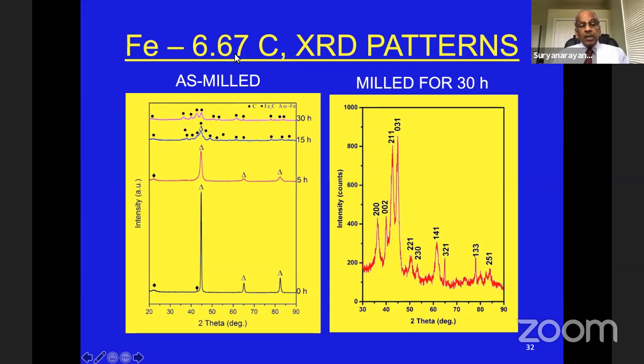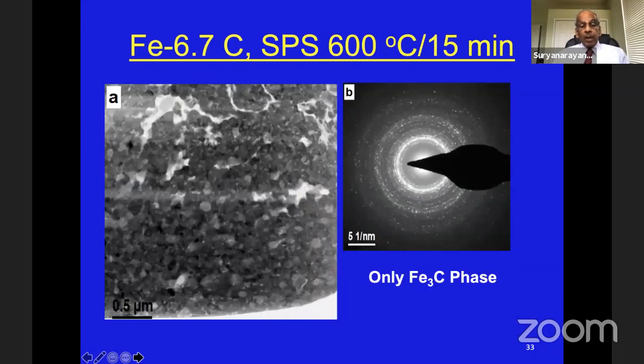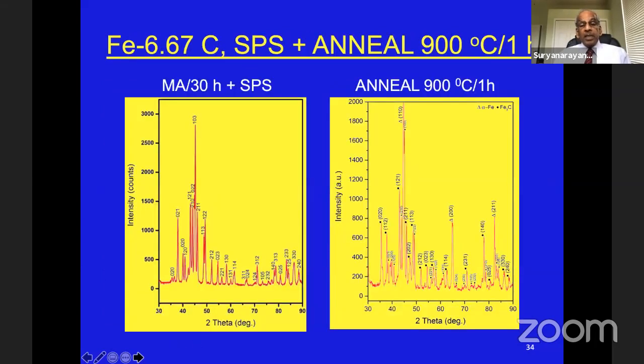Take iron, 6.67% carbon. You can see only cementite reflections in this particular case. And if you look at the TEM, you can see after SPS at 600 degrees, you can see equiaxed grains of cementite. And if you look at the diffraction pattern, you would see that only the cementite is there and no other phase is present in these materials.